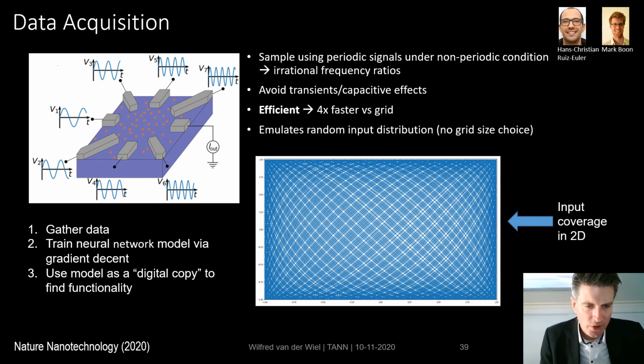A few more words on how to do the data acquisition for such a device, because you can imagine that you have to collect a lot of input-output data before you have a sufficiently good representing model. So what we do is we have this kind of parallel mechanism where we apply periodic signals to the voltage electrodes, and we do that so that the periodicities form irrational ratios. So the frequencies have irrational ratios. And here you see an example just for two parameters in the two-dimensional space.